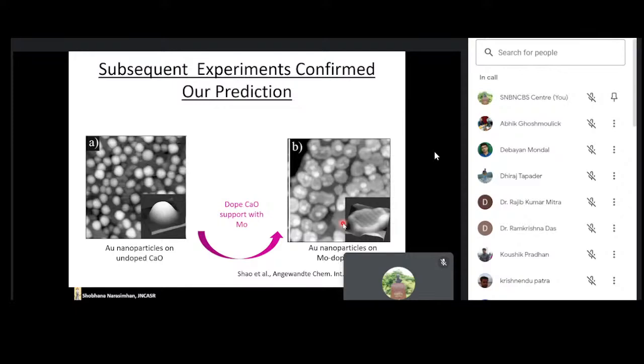So I've shown you two examples so far where a prediction was made by DFT and it was confirmed by experiment. And of course, we went on to confirm also that this is true for this system. And incidentally, these nanoparticles are much larger than 20 atoms in size. So that shows that this strategy works for larger sizes also. And we've also done calculations on smaller sizes and it shows that it works for smaller sizes too.